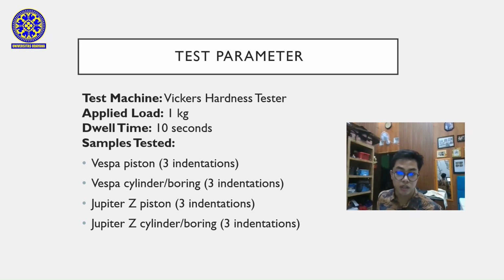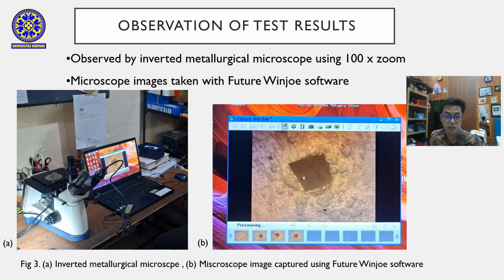In this experiment, the test was performed using a standard Vickers hardness tester. The load applied was 1 kg with a dwell time of around 10 seconds for each indentation. We tested 4 components: Vespa piston, Vespa boring, Jupiter Z piston, and Jupiter Z cylinder boring. Each component was tested at 3 different points to obtain a representative average. After testing, the test point results were observed using an inverted metallurgical microscope at 100 times magnification, and images were taken using Future Winjoe software.